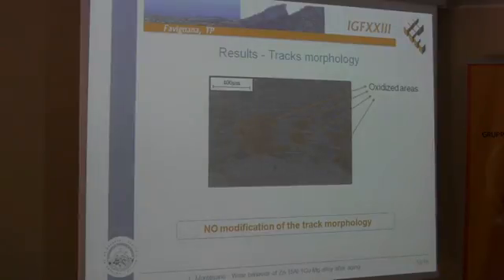The morphology of the track doesn't change with the aging time, so the decrease in wear behavior is probably mainly related to the decrease of the hardness of the material, as it is well known that by decreasing the hardness of the material, the abrasive wear increases.